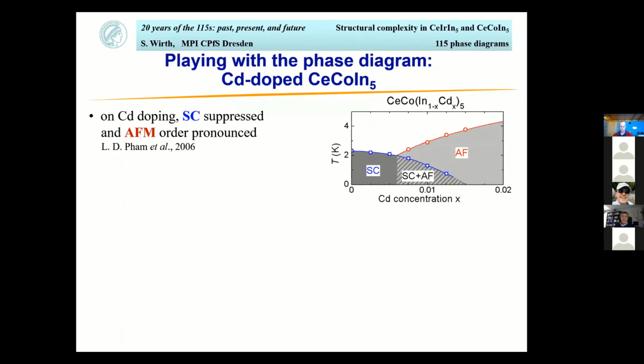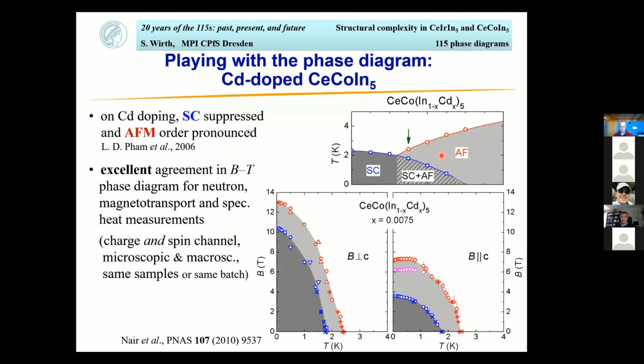Now, one other nice way of playing with the phase diagram was by putting in cadmium. That is a paper by the group of Zach Fisk from 2006. And you see with cadmium doping, you suppress the superconductivity and antiferromagnetism pops up. So we thought, okay, let's have a look at the sample here, which is at 0.75% cadmium doping, in which the energy scales of the superconductivity and the antiferromagnetism are actually pretty close to each other.